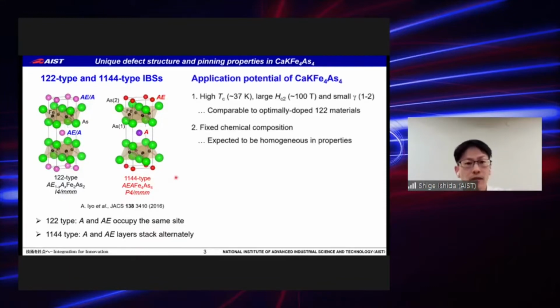Like the 122 materials, 1144 materials are characterized by high transition temperature, large upper critical fields, and small anisotropy, which makes them attractive in terms of high field applications. In addition, because the chemical composition is fixed to 1144, homogeneous properties are expected compared with 122 type.